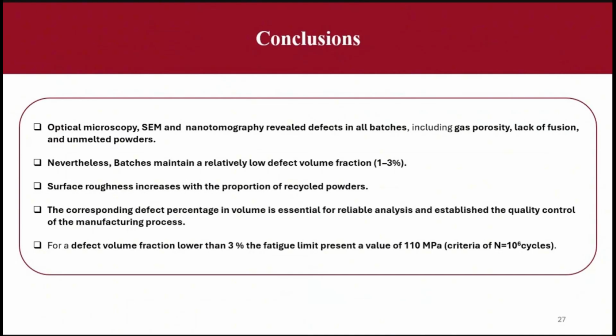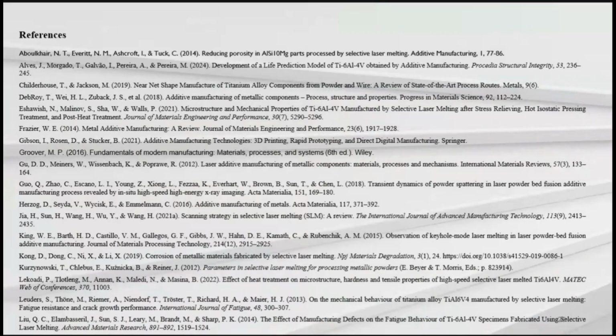For a defect volume fraction lower than 3%, the fatigue limit presents a value of 110 megapascal for the criterion. What I am observing when I read some papers is that the authors forget to say the criterion for failure and forget to say how many defects the material had. And this is important because the values are very different. Okay? So these are the references.